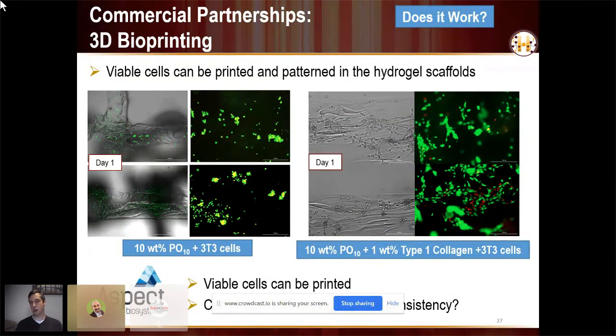And particularly if we add in collagen to give cells adhesion sites, since PEGMA is not great for printing cells in terms of the lack of adhesion sites that are present. We see better cell morphologies and a bit more proliferation in some of our longer days, which I'm not showing. But the key point here is we can print viable cells in patterns, and we're now starting a collaboration with Aspect Biosystems, which is a really unique and interesting microfluidic 3D printer, to try to control the mixing of these polymer precursors much better, and thus get much better mechanics as well as integrity of the final printed structures.